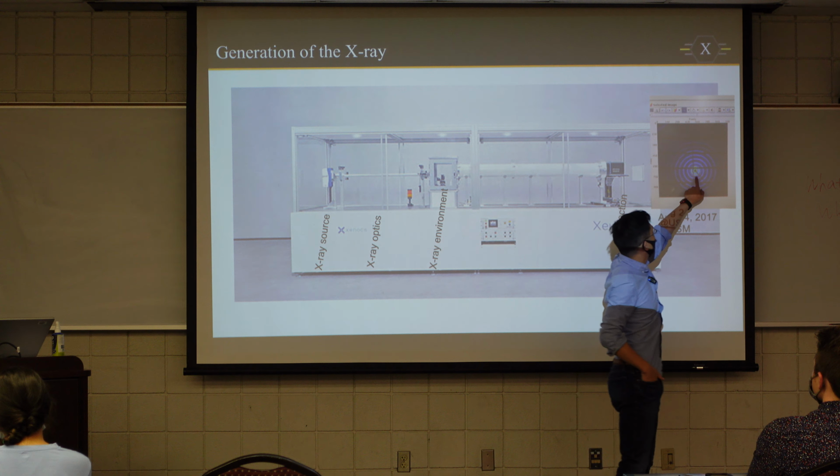If we know the sample to detector distance, and if we know how far our scattering is away from the center, let's call it L, or STD, and R, which is easy for everybody to understand, the radius from the center, you can calculate this theta: tan 2 theta equals R divided by L STD, right? So you just need to measure how far you load the sample away from your detector, and how far your material bends the X-ray from the direct beam.